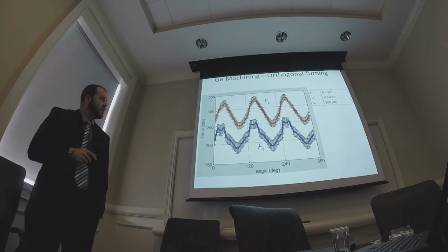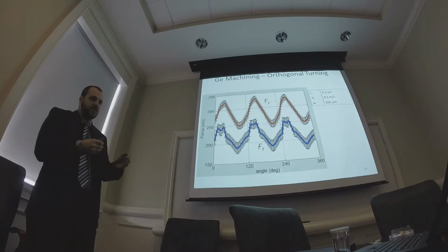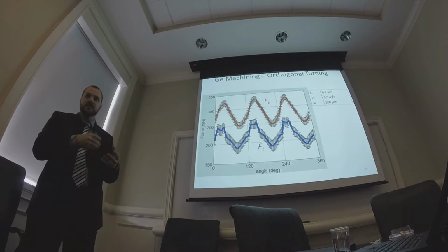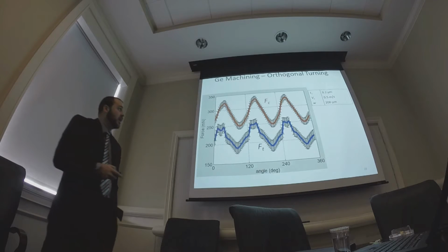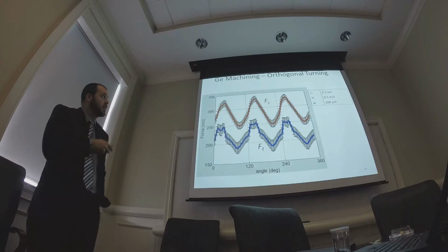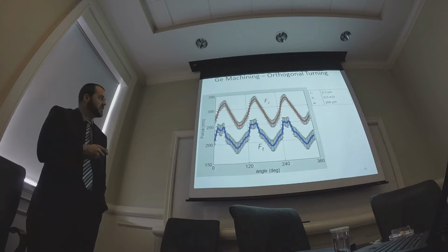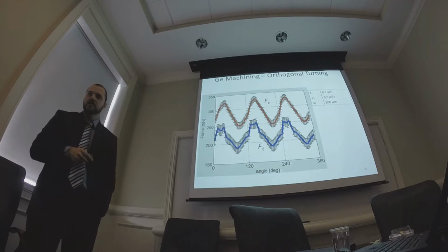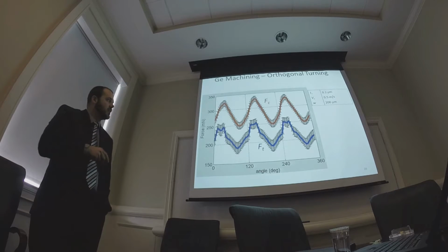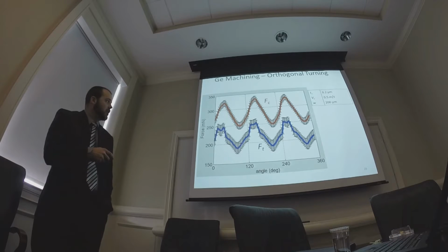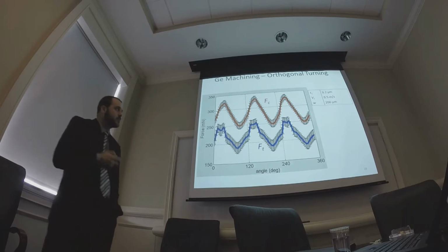The first thing I noticed when I pulled this up - well, you kind of have to optimize the speed because the speed wasn't perfect, so this kind of smears a little bit. But when you get this just right, you see the phase lag between what appears to be the bottom of the forces, and the top here lines up with this one, but not with the middle. So it's still unclear why the thrust force would be, say, low or higher as the cutting force gets to its minimum. That's kind of interesting.